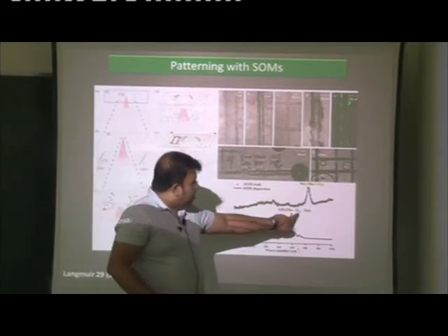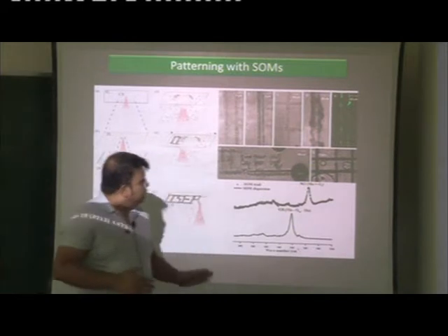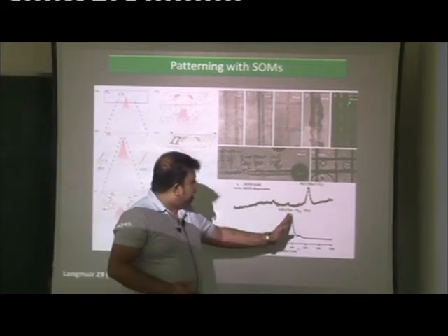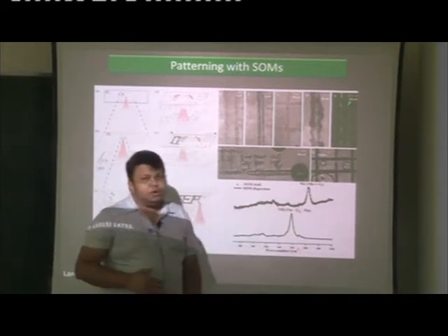And indeed, we find that the soft oxometalate undergoes a crystalline phase transition, which we see from Raman spectroscopy. Where we see the molybdenum-oxygen bridging with molybdenum, this band completely disappears, and a molybdenum-oxygen terminal stretch appears. So we have a clear phase transition from the tubular soft oxometalates to crystalline polyoxometalates.